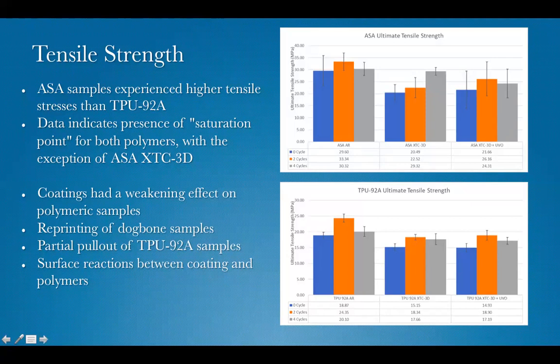Rather, coated samples tended to actually be weaker than uncoated samples at all stages of experimentation. Moreover, many sample groupings actually experienced an overall increase of strength over time, with a sharp increase from 0 to 2 cycles and then a slight drop off from 2 to 4 cycles. These unusual findings may be due to a number of factors, including a faulty batch of 3D printed samples, deleterious surface reactions between coating and sample, and poor fracture mechanics, especially in regards to the TPU-92A samples.